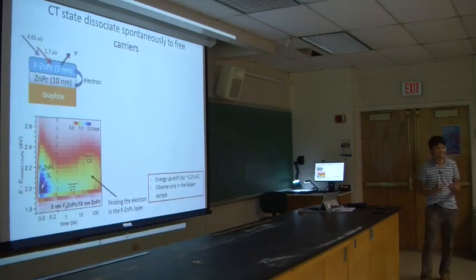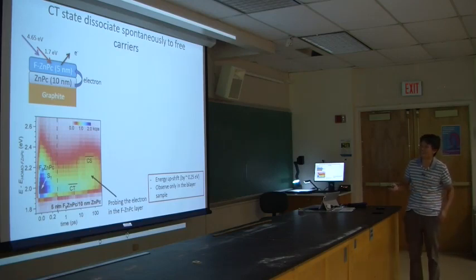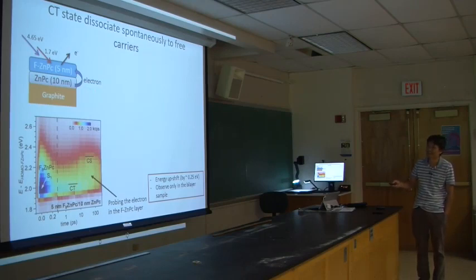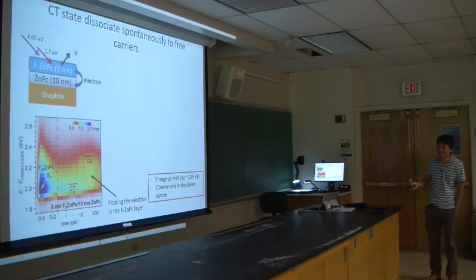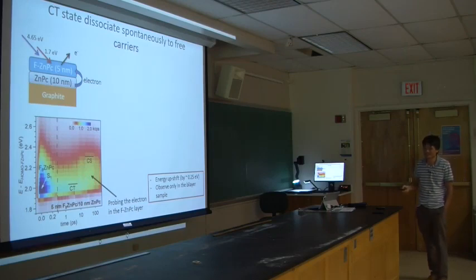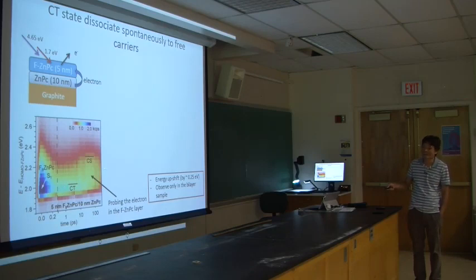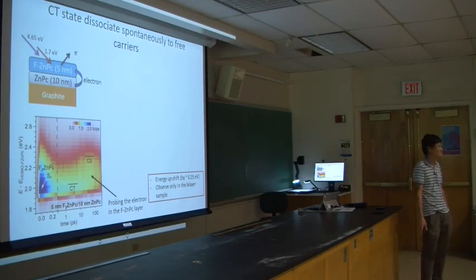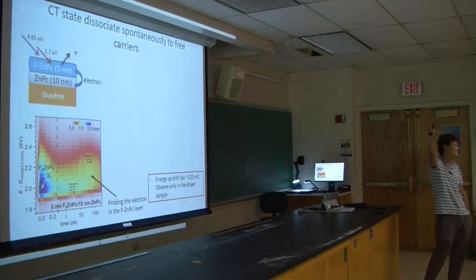But actually, we were surprised by what we saw. So what we did is, again, we excite this donor acceptor, right? In that case here, we excite both, actually, but we can study the electron transfer to the top F-ZnPc layer, right, which is an acceptor. So we're probing the electron in this charge transfer exciton. The main difference from the previous one is that we first excite this lower energy CT state, and then later the energy actually goes up instead of going down. It's like these energy uphill reactions, right?